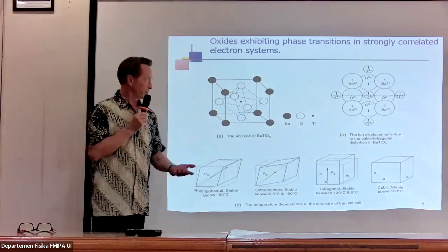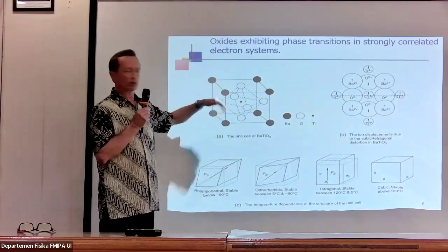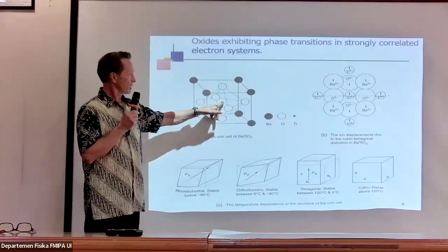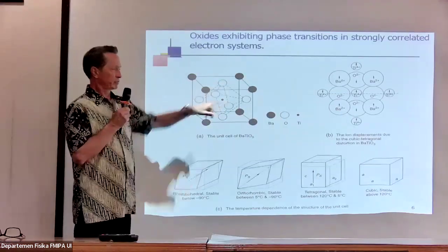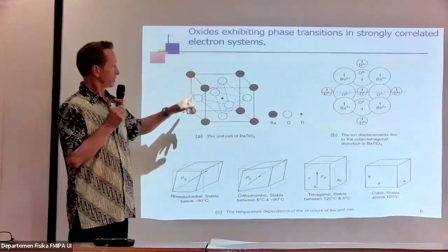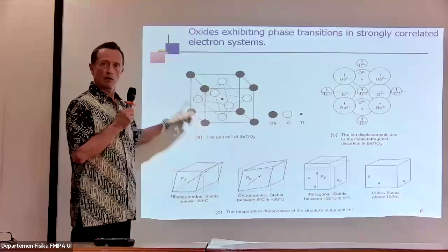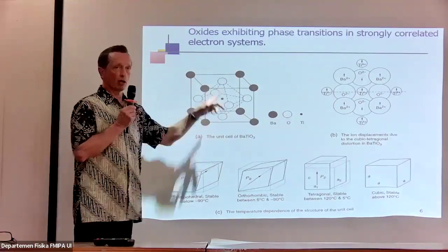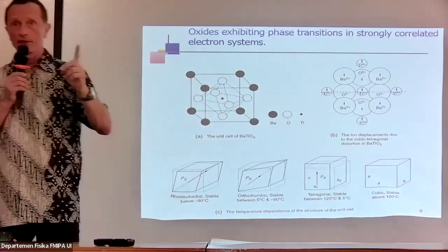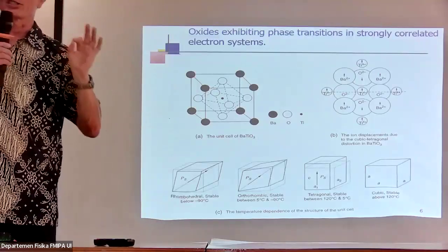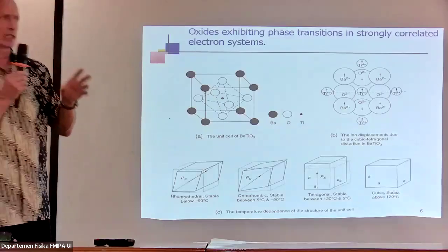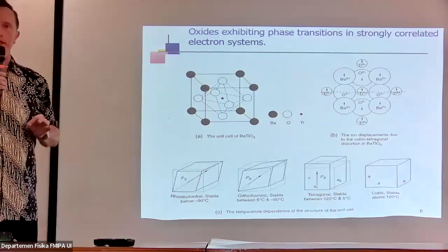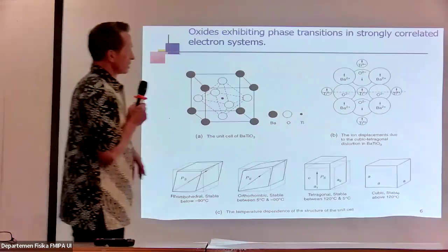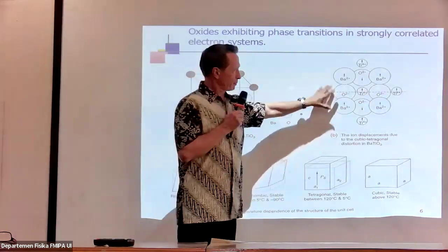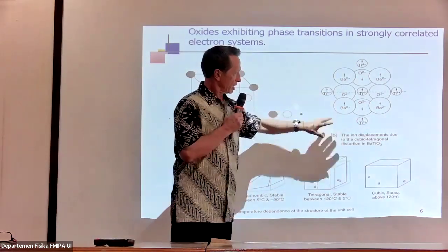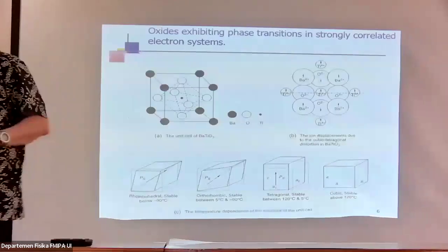So that means the defects can be, you can have a lack of anions or cations in the corner or here in the center. You can have some impurities that replace the different ions, or you can have a lack of oxygen. That means the octahedron is not filled with oxygen. You have what we call oxygen vacancies. And these oxygen vacancies will influence especially the conductivity of the material.